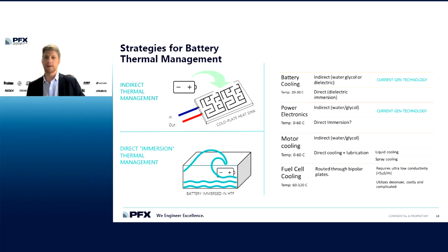The second strategy is direct immersion thermal management. In this case, we remove the indirect heat sink. The battery pack is submerged directly in the fluid. So think of a bathtub and the battery cells just getting put directly into it. So these types of fluids require a whole other level of electrical insulating properties. So when we talk about less than 100 microsiemens fluids, that is not sufficient to be a direct immersion fluid. These are typically oil-based fluids that do not carry current at all, practically. So you have to have a very, very insulating fluid. The benefit of the immersion cooling strategy is you get complete surface area coverage of that battery cell, which is generating heat, so you can remove heat more efficiently.